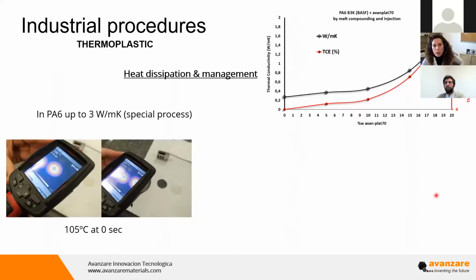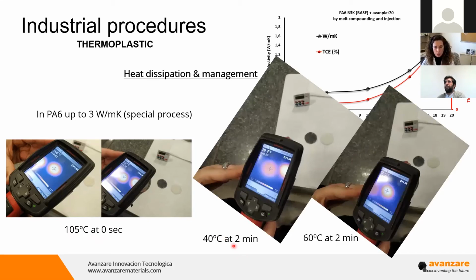Some applications that we can observe in different areas, for example, this is thermoplastic. What we are seeing in the image is two materials: neat polyamide 6 and one polyamide 6 with graphene. To see graphically how this is working for heat dissipation and management, we heat at the same temperature. At the initial time, you see that it's up to 100 Celsius degrees. We record the temperature with the infrared camera, and after 2 minutes, what we see is that the neat polyamide is remaining at about 70 Celsius degrees, while the one reinforced with graphene is 20 Celsius degrees below. So this kind of application is useful for accelerated cooling processes of materials.